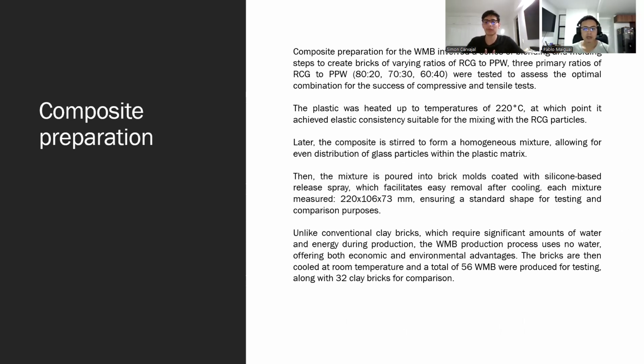Composite preparation. The composite preparation of the WMB involved a series of blending and molding steps to create bricks of variable ratios of RCG to PPW. The plastic was heated up to a temperature of 220 degrees centigrade, and later the composite is stirred to a homogeneous mixture. The mixture is poured in brick molds coated with a silicone-based releasing spray to facilitate easy removal after cooling. Unlike conventional clay bricks, which require significant amounts of water and energy during production, the WMB production process uses no water.